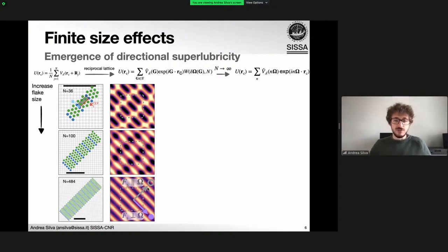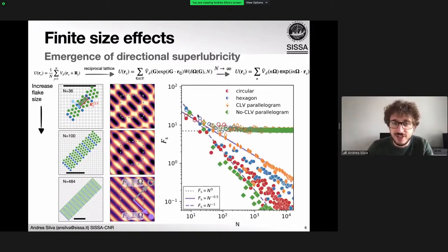Now we can go back to a bit more friction and measure the friction along the two directions, parallel to the valleys or perpendicular to them. And what we find is that the friction scales very differently. We have a finite friction per particle, so it's constant, perpendicular to the valleys, while along the corridor, as the size increases, it scales sublinearly. We tested numerically how this goes for different shapes, and we see that it nicely stays between the theoretical boundary, which has these two lines.